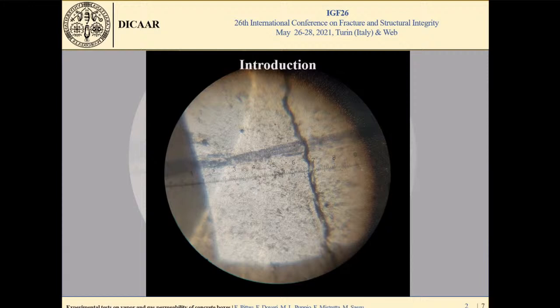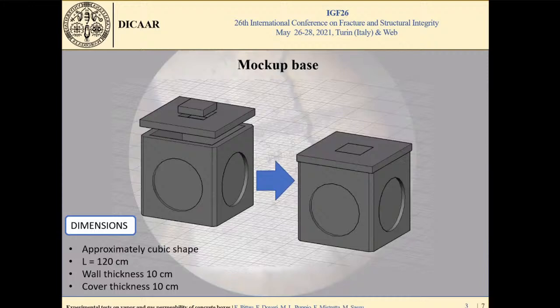The second phenomenon that produces permeability is shrinkage. The aim of this work is to present the results of a first step of investigation on some experimental tests of 4 concrete boxes characterized by 4 different external coatings. The goal of this research is to explore this field in order to limit the vapor permeability and to ensure tightness of the concrete walls. For this purpose, 4 specimens with approximately cubic shape are tested, and the mockup is arranged, as you can see, using some concrete cockpits, usually applied in water discharge management.